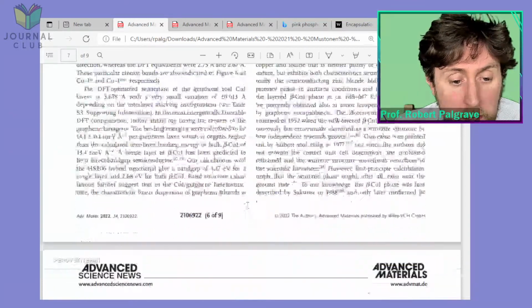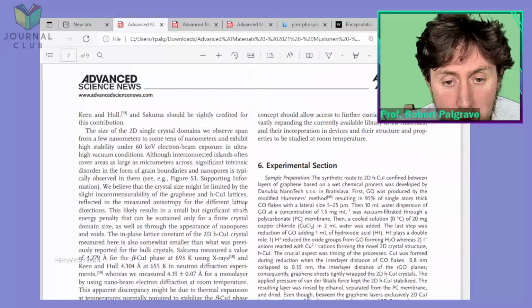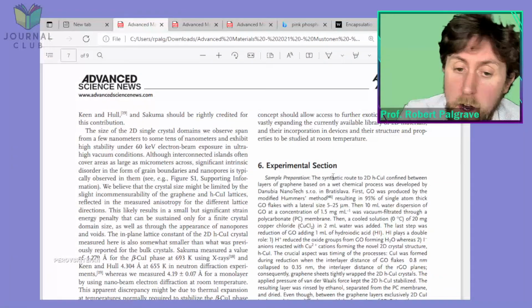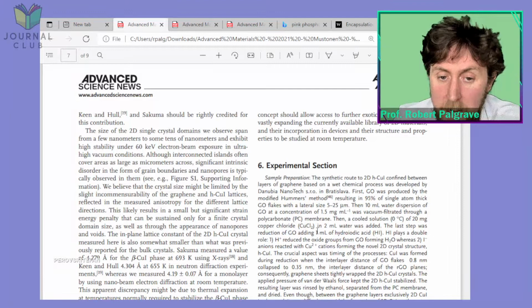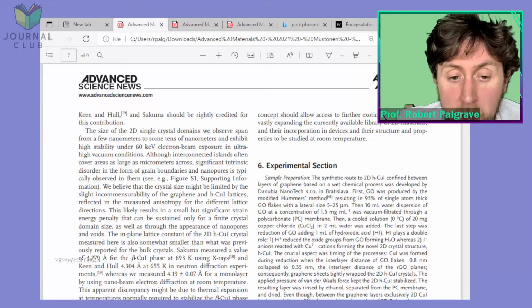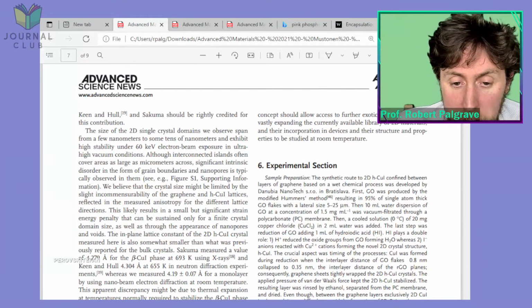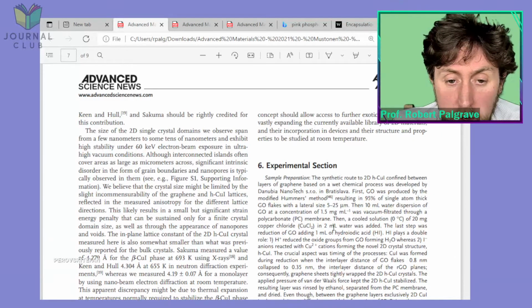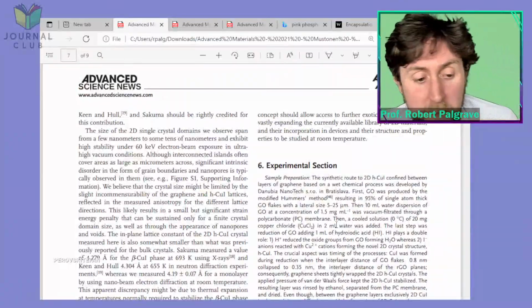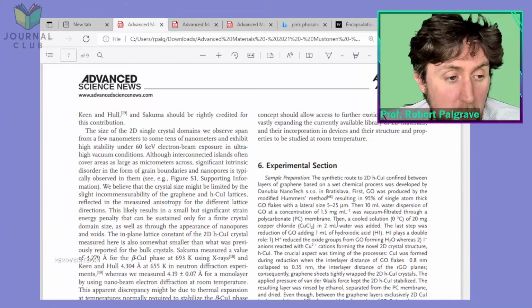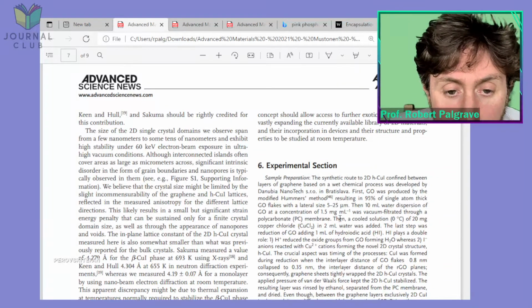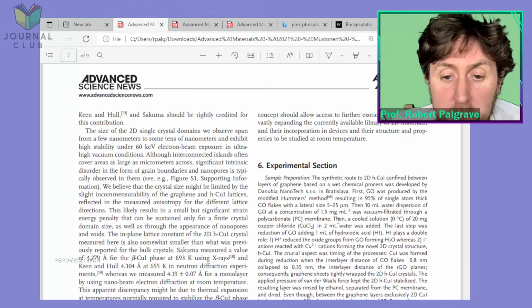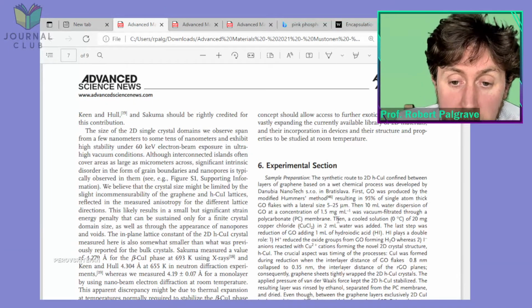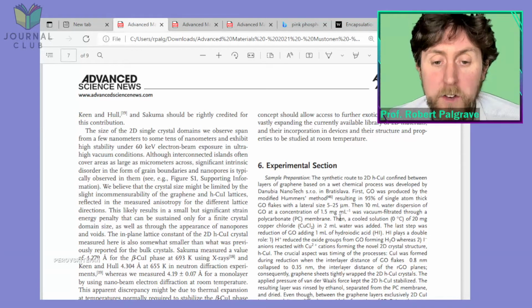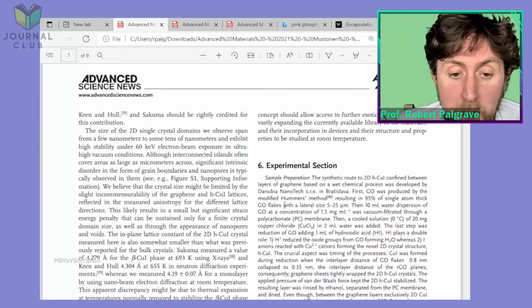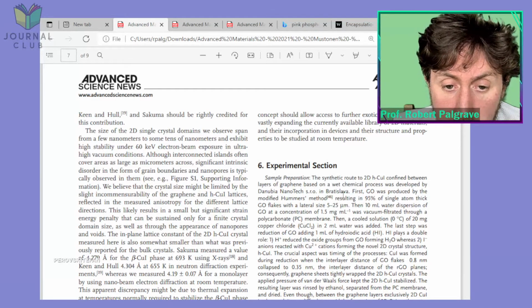So what I did say I would do is go and have a look at the experimental, because I'm actually pretty interested in how they did this. How difficult was it exactly? So I think they've written quite a nice experimental section here. So I'll just read about sample preparation. I don't really care too much about how they did the TEM. Obviously that's important. And if you're a TEM nerd, then by all means go and have a look at that. But sample prep. So the synthetic route to 2D hexagonal cuprous iodide, confined between layers of graphene based on a wet chemical process, was developed by these guys in Bratislava. Okay, first GO.